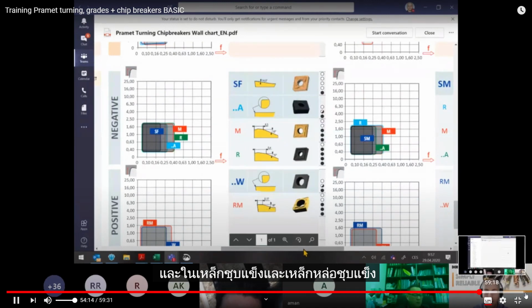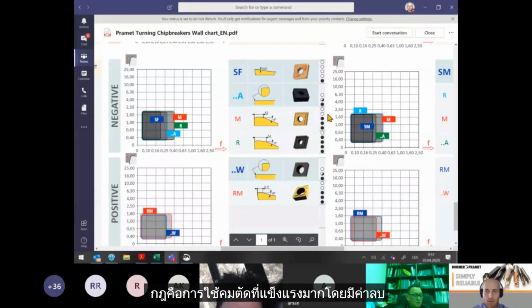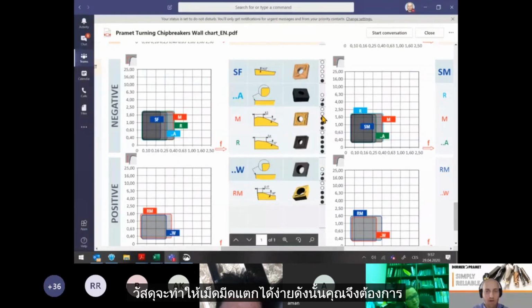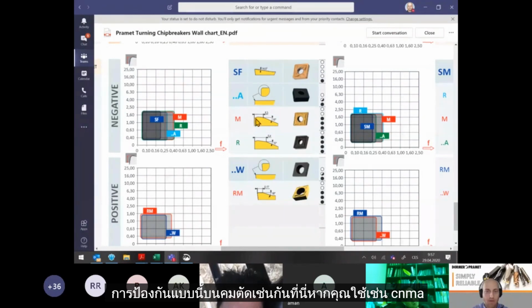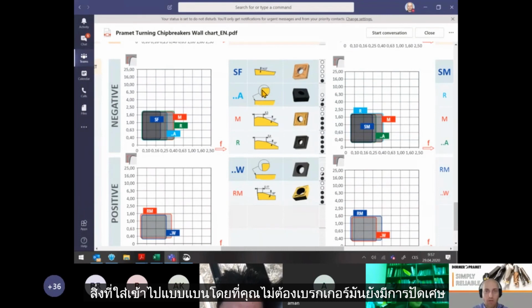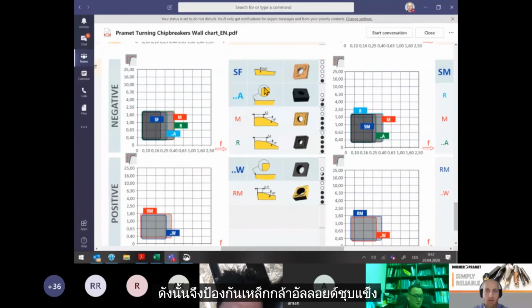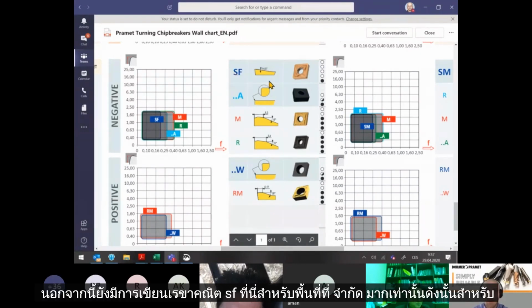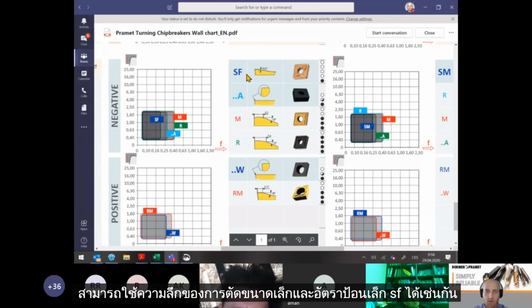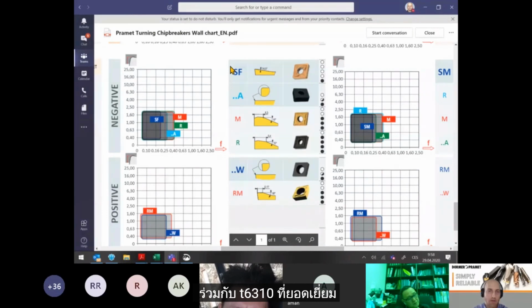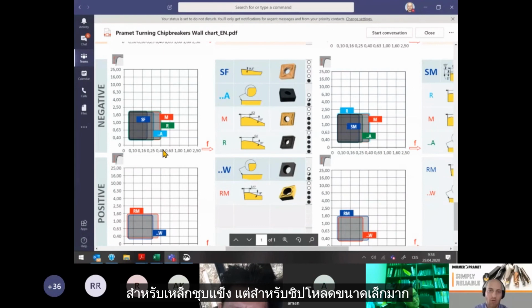And in hardened steels and hardened cast irons, the rule is very basic: use a very strong cutting edge with negative T-lands, because the high strength of the material will easily break the insert. So you need this kind of protection on the cutting edge. Also here, if you're using something like CNMA, a flat insert without chip breaker, it also has rounding, so it's protection against hardened alloy steels. There is also SF geometry written here. It's only for a very limited area. So for small depth of cut and small feed rates, SF can also be used in combination with grade T6310 for hardened steels, but for very small chip load.